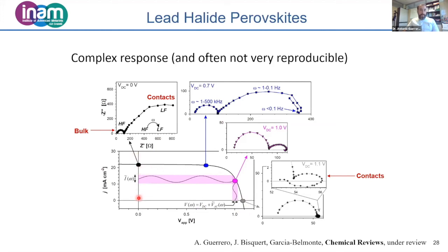And we apply, we measure impedance at 0 volts, at 0.7, at 1 volt, and at VOC conditions. Here, as you can see, there are different features depending on the DC voltage, and this is because the operation mechanism at the different voltages is different. So in this case, we are extracting most of the photocurrent, and in the impedance response, we see two arcs. We see one high frequency arc and one low frequency arc.